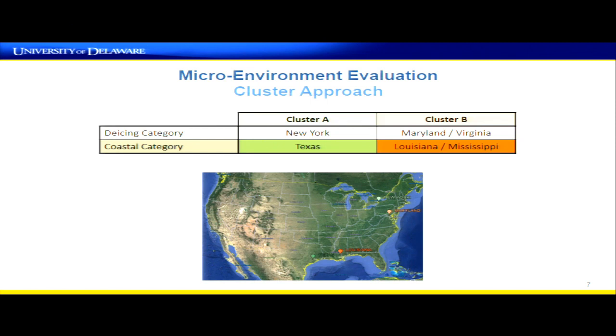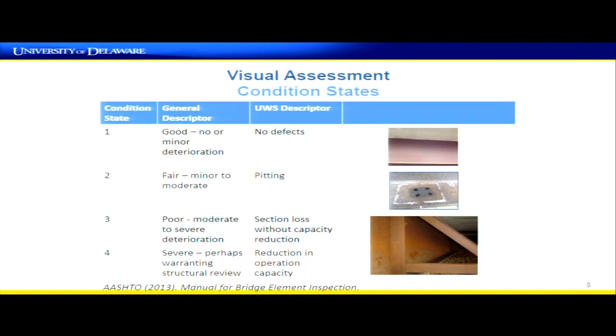And then there's also places where the weathering steel was performing not as well as the owner expected, and there really wasn't any obvious reason why that would be. So we were really focused on trying to understand outliers in performance, and there was a very robust statistical analysis used to select these. And so here we're looking at very detailed inspections of each of the bridges within this cluster. So for example, just looking at superstructure condition from the NBI for thousands of bridges, now we're looking at very detailed evaluations for a smaller number of bridges. So really 2 opposite ends of the spectrum here.